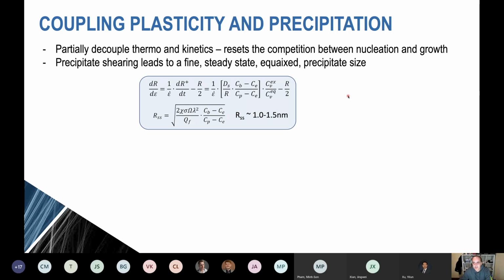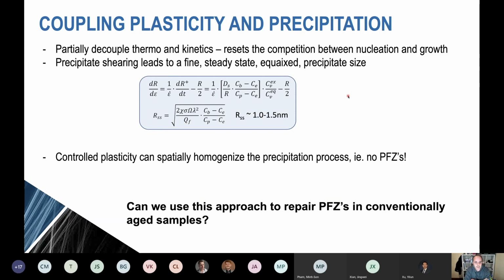Perhaps the most interesting thing for me, and the reason I got really involved in this in the first place, is that by using dynamic precipitation and controlling the plasticity, we can spatially homogenize the precipitation process. Now, think about this. Dislocations move in our microstructure wherever it's most easy for them to move. And that is where they will generate vacancies. And if there's solute available, then they will drive dynamic precipitation, which will strengthen that region. So generating a microstructure in this way using plasticity, it is self-regulating in both space and time, and so it leads to extremely uniform microstructures. And indeed, the sorts of microstructures that I just showed you, these materials don't have precipitate-free zones. And that's a big, big plus for aluminium alloys.